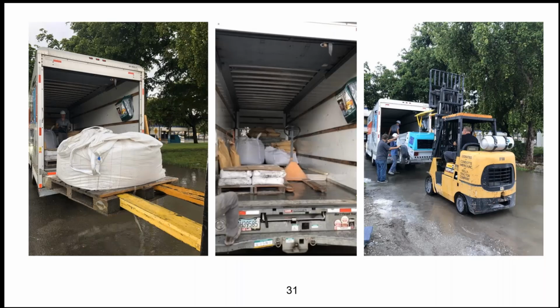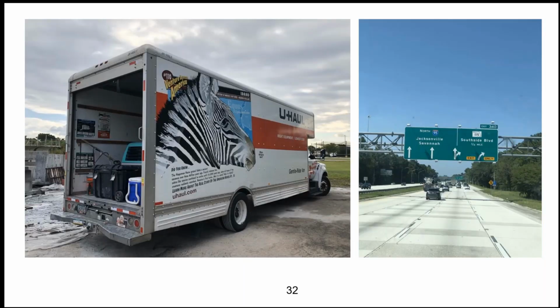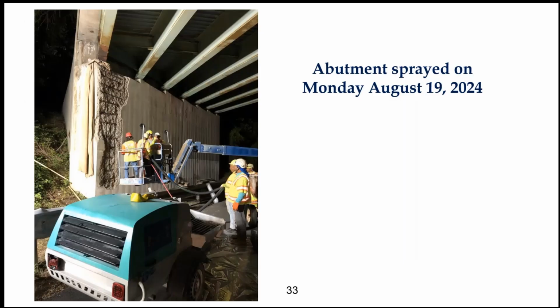So based on that, we got all the material, and we are using the ABC-UTC open source UHPC data. So this is not a commercial version. This is just the open source mix that we have developed, and we measured everything. We shipped it to Northern Virginia near the Washington DC area, together with our equipment that has been modified.